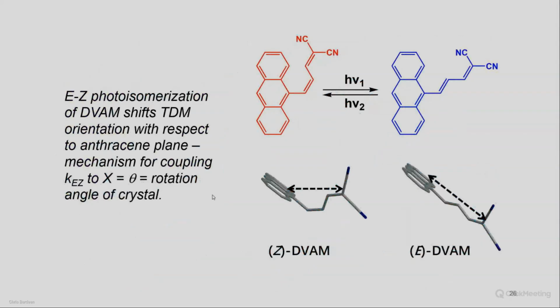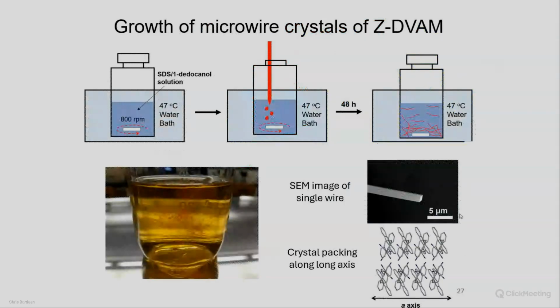So this was the guy, and this is the transition dipole moment orientation. We actually start with the cis isomer in this case, and it rotates to the trans isomer, and you get a rotation of the transition dipole moment. We're assuming that the anthracene stays the same, and we're just rotating this conjugated tail within the crystal frame, right? So none of this would work if you weren't in the crystal. It's the crystal that gives you this preferred orientation of the transition dipole moment, that gives you the anisotropy that you need. And you have to grow the right type of crystal.